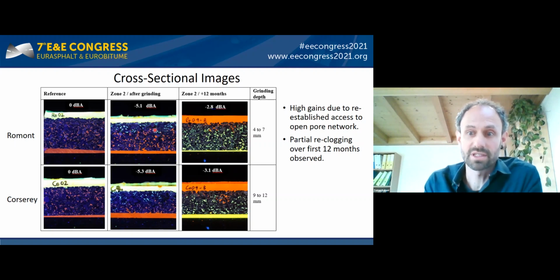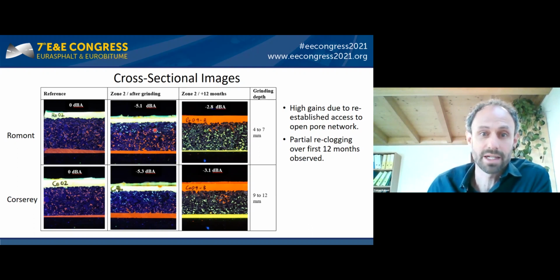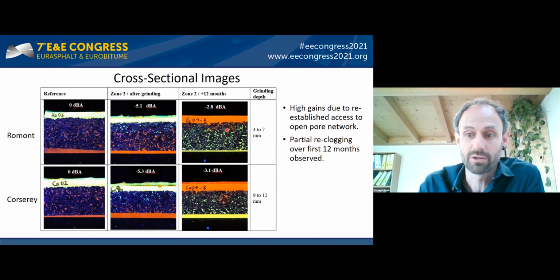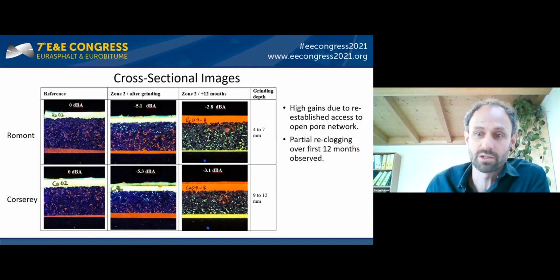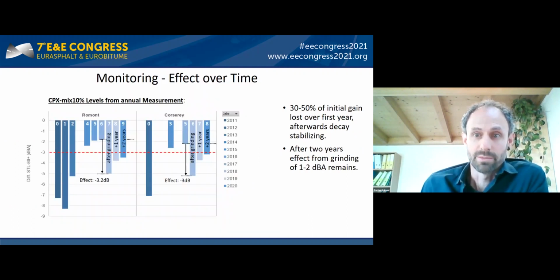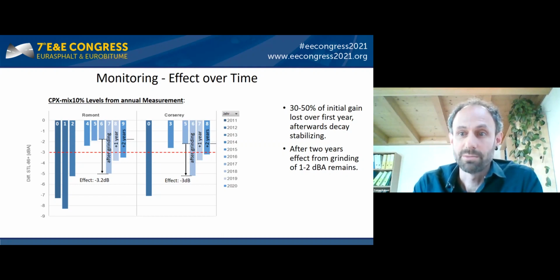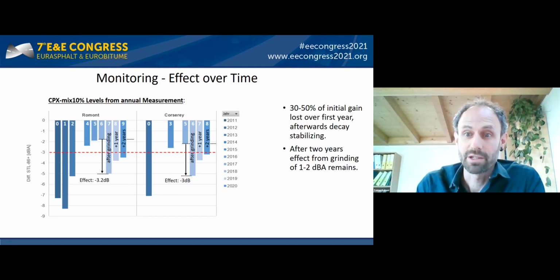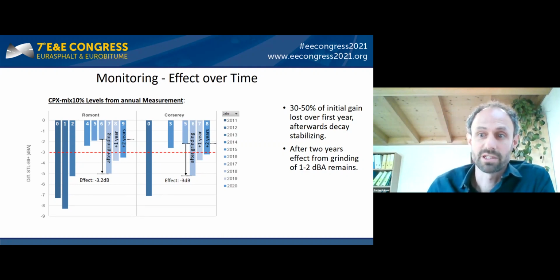We can conclude that the high gains of up to minus 5 decibel are due to re-established access to the pores. After 12 months, partial reclogging occurs, which is observed by the somewhat decreasing penetration depth of the resin. In this case, it's now the red color. The measured gains of 3 to 5 decibel can definitely be considered as a high acoustic benefit, but the big question is how long will it last?